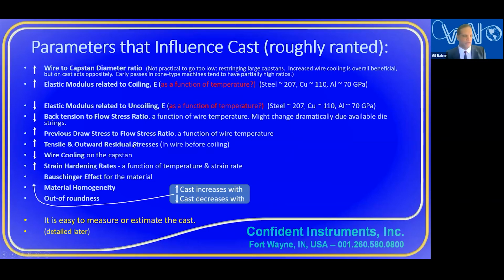Now there's also the issue of residual stresses. Even if they're axisymmetric, the tension from the residual stresses near the surface of the wire is going to influence your coiling and your uncoiling. Actually, it's going to be worse. So the cast is going to be higher with more tensile residual stress, even if they are axisymmetric. Again, they could be asymmetric from previous dies, as I showed before. The wire cooling on the capstan is going to have an influence. Now, I've kind of gone down here. There's lesser and lesser influence as we go down, but I'm just listing everything. But again, the main thing is just to get out and measure the cast. And that's probably most important, because someone can make a model.